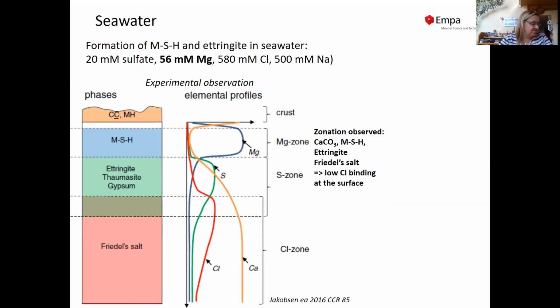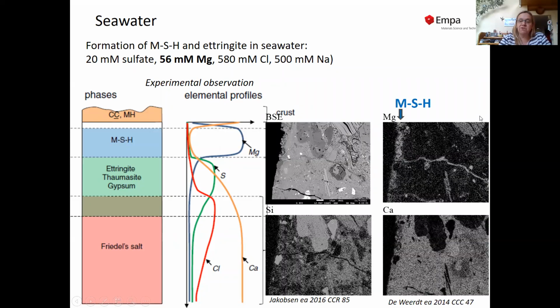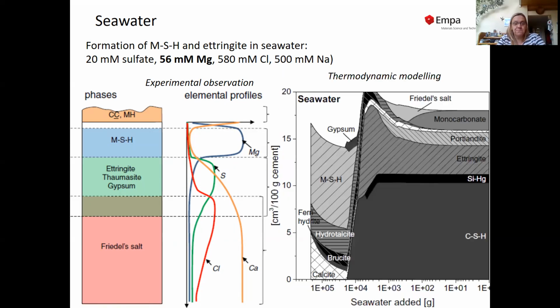If we go to seawater, things get much more complicated, because seawater contains not only sodium chloride, it also contains significant amounts of sulfate and magnesium and carbonates. And this we can see here on a schematic picture developed by Jakobsen et al., where they've seen a sequence of first chloride accumulation near the center of the samples, then a sulfate attack, followed by an accumulation of magnesium. And we can see this magnesium accumulation also in elemental plots, as shown here, where we start to see a clear formation of a magnesium silicate layer.